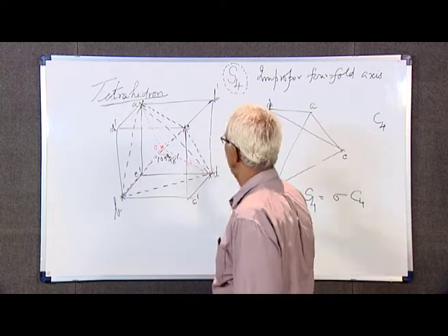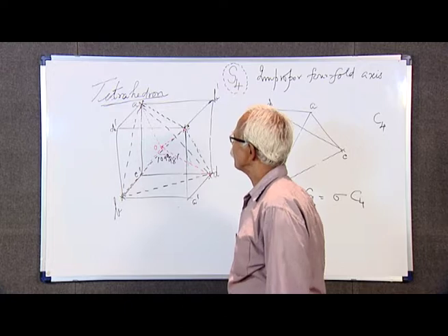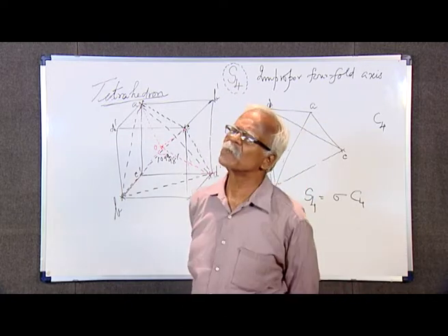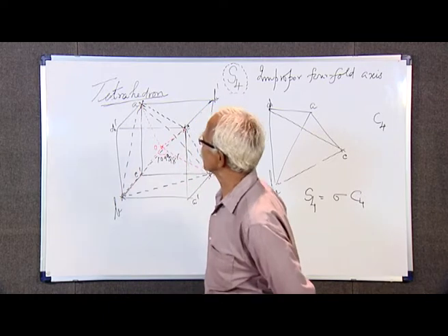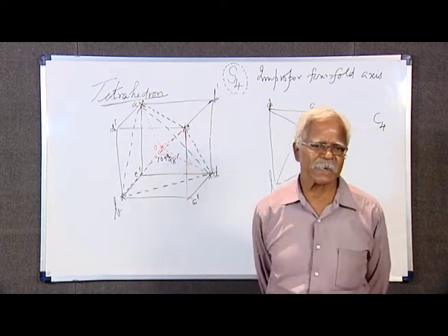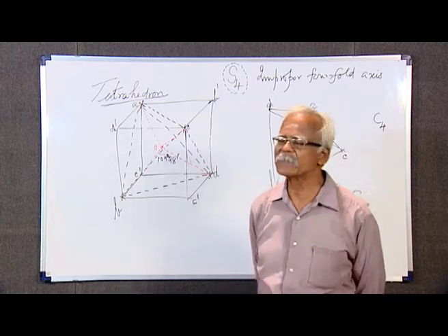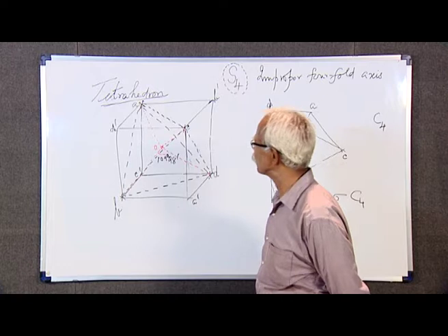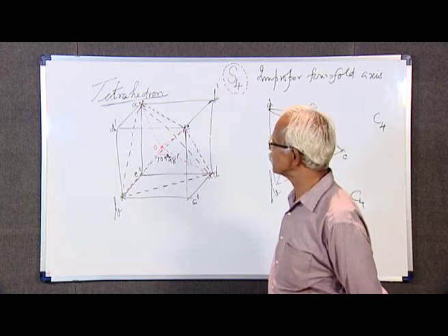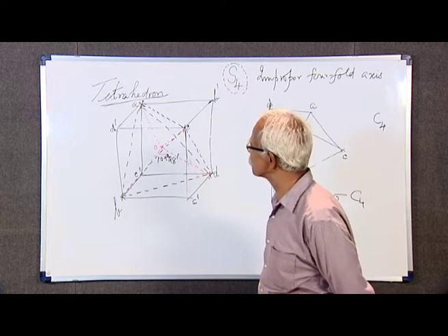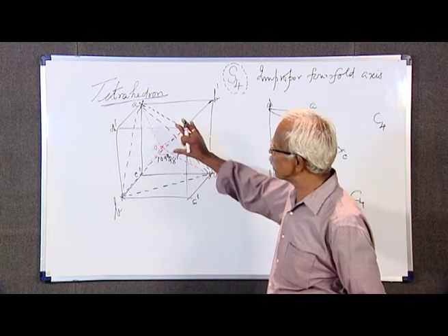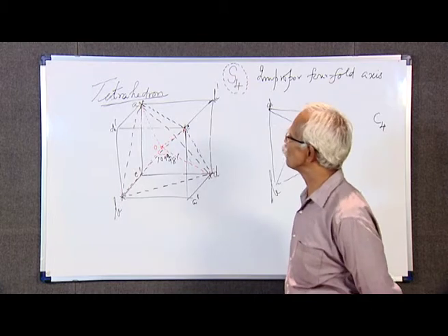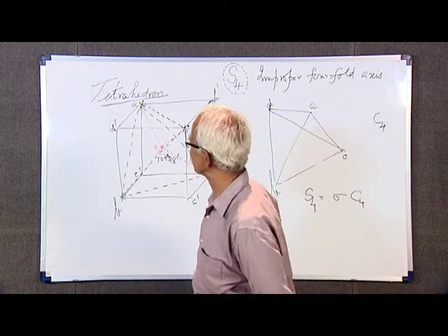Of course, often in the textbooks one will see a statement that a diamond structure involves an FCC lattice with a diatomic basis, such that if one carbon atom is at 0, 0, 0, the other is at 1/4, 1/4, 1/4. That statement is perfectly okay, but it can best be understood in terms of the tetrahedron inscribed inside the cube.